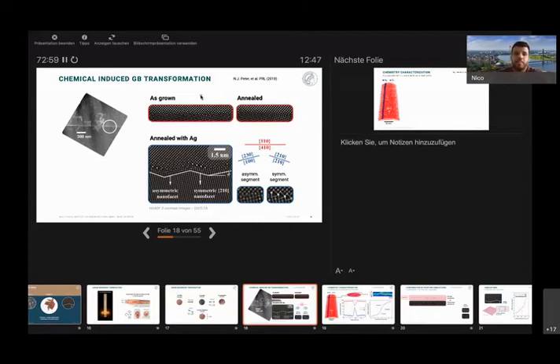And especially in STEM, if you have two grains that are not perfectly in zone, or one is perfectly in zone axis and the other one is not, then the one in zone axis is brighter than the other one. And the more you get out of zone axis, the less you will see until you only get a gray background. So probably in these two images, there was a little twist component of the grain boundary of the two grains relative to each other, and this one is not perfectly in zone axis. If that answers your question. Yeah.